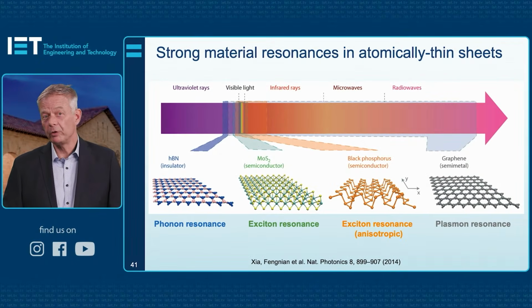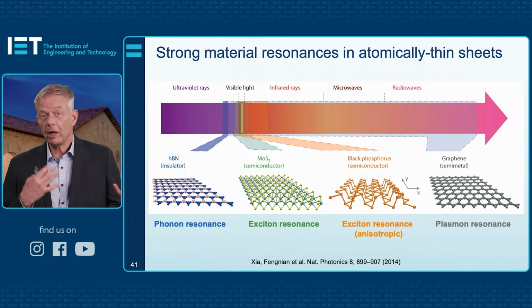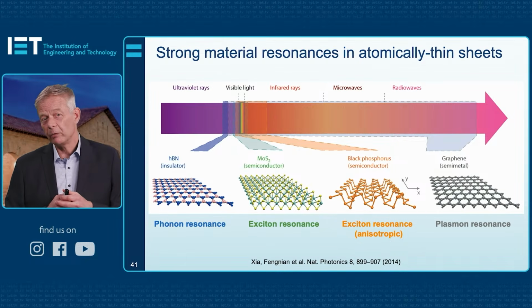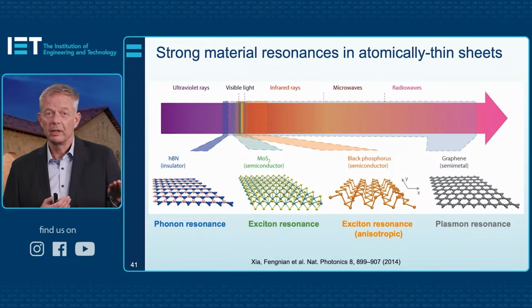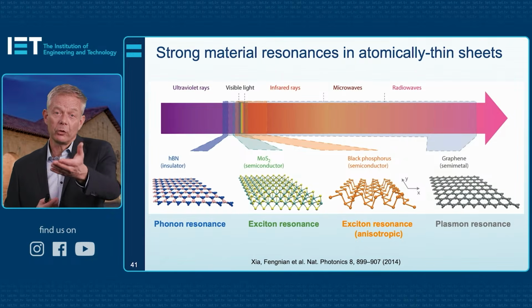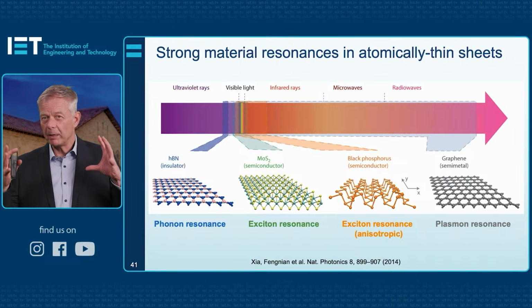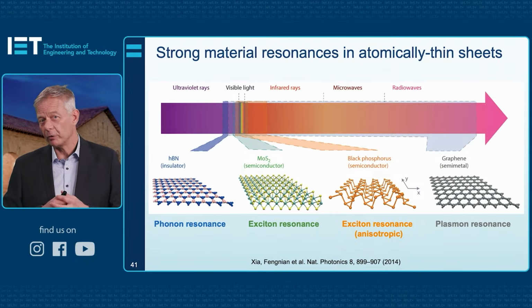Now, there's a larger opportunity here as well for the larger 2D and optoelectronics community to see whether we can harness not only the exciton resonances that we've seen, but there are also lattice resonances, phonons, lattice vibrations that maybe we can harness to manipulate light. We can also maybe use plasmon resonances, not in big metallic particles, but atomically thin layers of graphene. I think an entire field is starting to open up with many players where we can start harnessing not only metal nanostructures and semiconductor nanostructures, but also these beautiful two-dimensional materials and see whether we can start applying them more in optics.